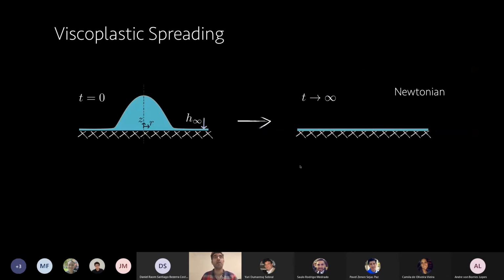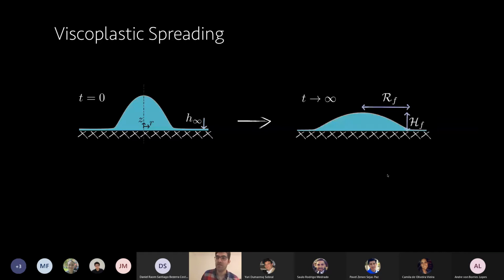Okay, I told you also in the very beginning that if you put a droplet on a Newtonian film, it spreads until it goes to infinity, right? So you get a flat film. But for viscoplastic fluids, it is not the case. So the droplet spreads until the stress inside the droplet comes below the yield stress everywhere. Therefore, you reach this final shape that features this final radius RF and final height HF.